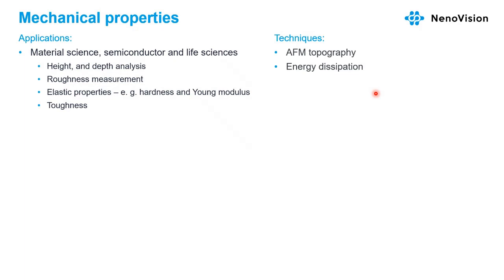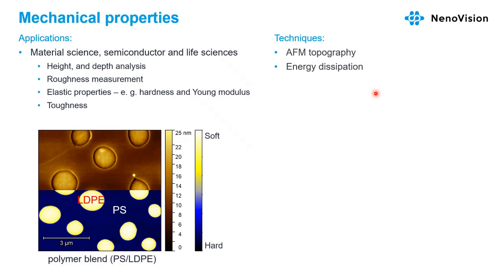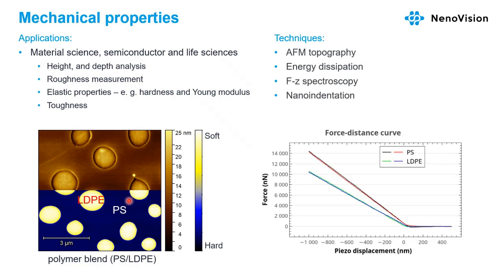These properties can be measured by atomic force topography, elastic properties by energy dissipation for the mapping. We see the topography image in the upper part, and energy dissipation in the lower part of a polymer blend, polystyrene and the polyethylene. So we see that softer is polyethylene than the polystyrene in this case. Another technique used for measuring elastic properties is force distance spectroscopy or nanoindentation, where we apply the force and get the graph from which we find Young modulus, the hardness, toughness, etc.